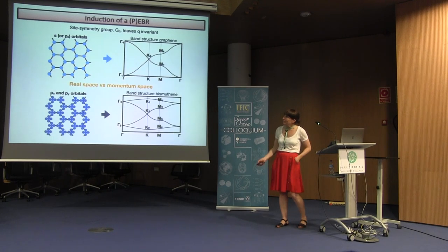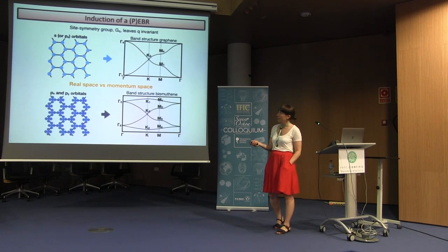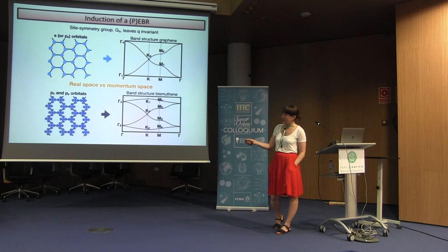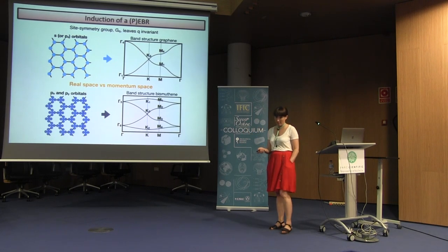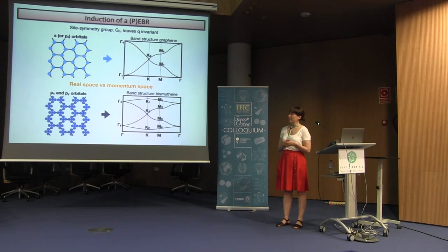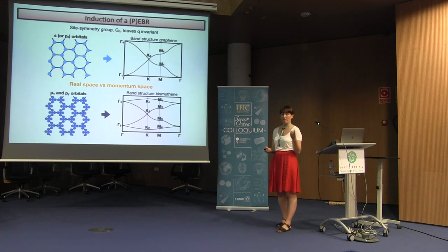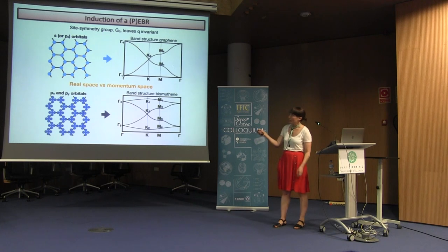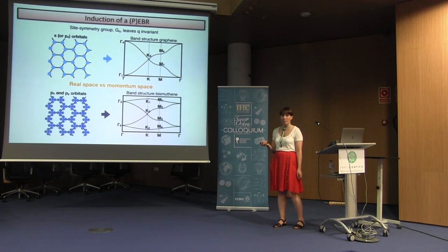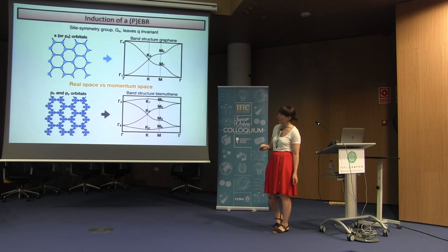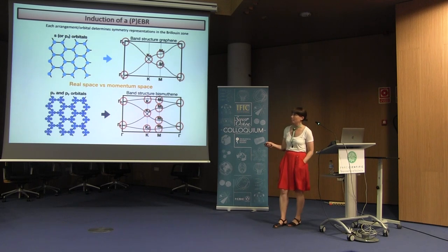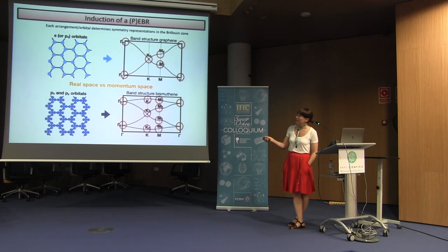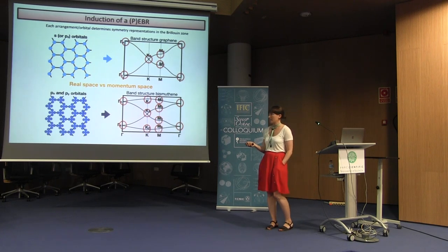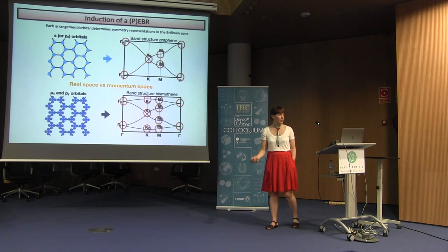All right, so, when we do this procedure that is an induction, depending on the symmetries of the lattice, we're going to have one set of bands or another set of bands. So an elementary band representation is defined by the space group, the position of the atoms in the space group, and the orbitals. And when we Fourier transform into reciprocal space, at the high symmetry points, the wave function is going to have different properties depending on the orbitals. And these different properties have been classified. So the information I get by using an elementary band representation is the symmetrical properties of the little groups at the high symmetry points. And because it's an elementary band representation, I know that all these bands need to be connected by definition.